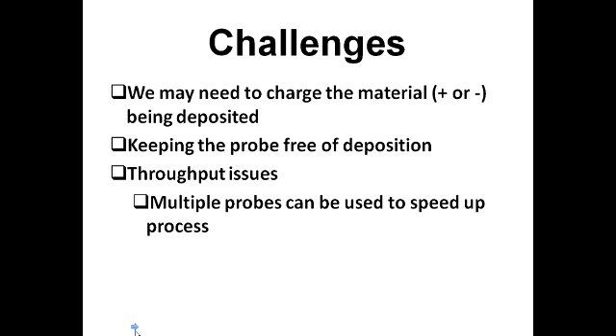There are some challenges with using this method. One of them is that we may need to charge the material positively or negatively, and keeping the probe free of deposition is very hard. Maybe we need to coat our probe with some special material to prevent the deposition of metal on our probe. And throughput is very important. Maybe we couldn't make a lot of features by this method. We could use multiple probes to speed up our process.